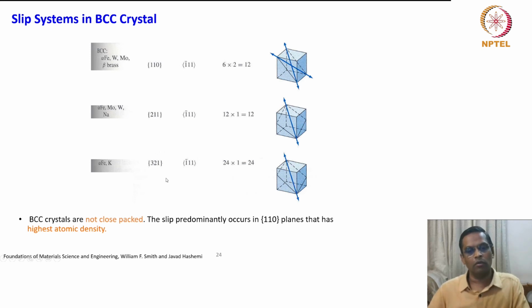And the third slip system which BCC exhibits is 321 planes and 111 direction, giving rise to about 24 systems, like in alpha iron and potassium. All these directions are marked here for rough reference. So if you look at the number of slip systems compared to FCC, they are more. But the problem is BCC crystals are not close packed. The slip predominantly occurs in 110 planes, which have the highest atomic density. So you have to remember that.